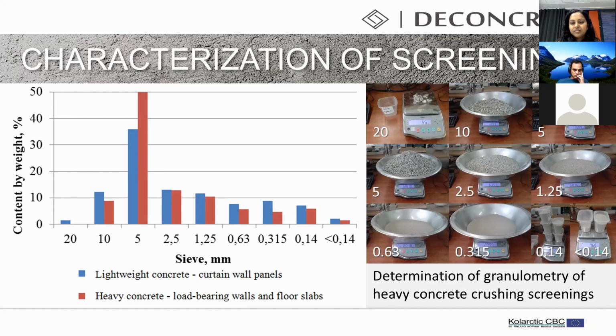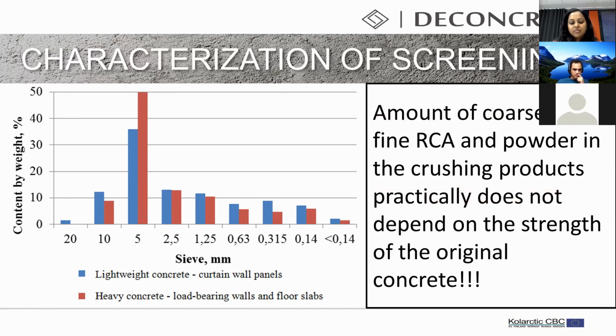But looking at this characterization of screenings, we can make one important conclusion. No matter lightweight concrete or heavy concrete, the amount of coarse RCA, fine RCA, and concrete powder in the crushing products practically does not depend on the strength of the original concrete. So we can grind and mill lightweight concrete and heavy, and we will have the same granulometry. So it's a very important conclusion.